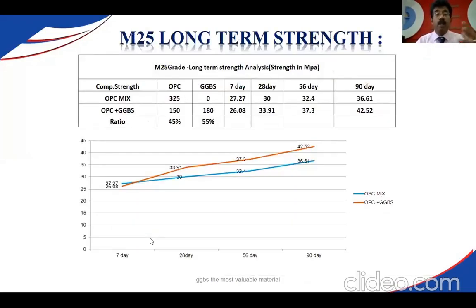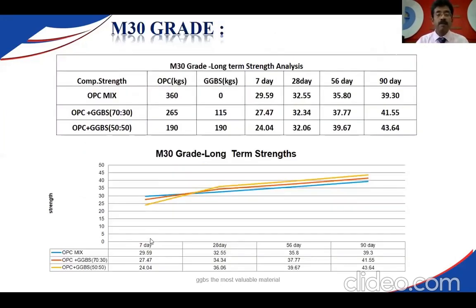Similarly, we have done it for M25 grade concrete. You can see how the results are going. At 7 days it is almost equivalent. Here the replacement is OPC 45%, GGBS 55%. We are using a component more than cement here. So we have studied the long-term strength up to 90 days. We can clearly see the graph showing better strength parameters compared to your regular concrete mix with cement. M30: generally, these are the grades we use in most of the cases. Higher grades of concrete, we have better, more strength.